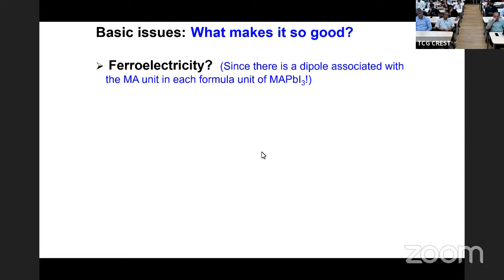So the question one asks is, what does this dipole do? Every unit cell has a dipole. Do these dipoles arrange themselves in a periodic manner in a ferro way, all the dipoles pointing the same way? Because if they did, then it's a polar material, and it could also be ferroelectric and switchable by applying a voltage, and that would help in separating the electron and hole, because the electron will try to go to one end of the macroscopic dipole of the ferroelectric material and the hole will try to go to the other end, so you will separate out electron and hole very quickly.